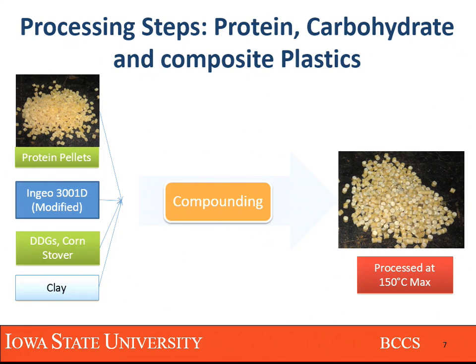So once we got all of these protein plastics compounded, you had to bring them down to a certain moisture level. In plastics compounding, everyone knows that moisture is one of the parameters to control. Having compounded these protein pellets with high moisture content of almost up to 30 to 40%, we had to bring them down to the 5 to 6% range so that they are both plasticizable and at the same time can blend with other materials like PLA or PHA and such.